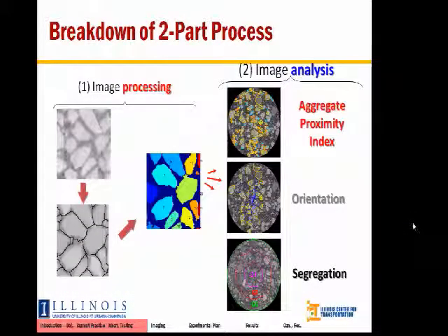But what is happening in a very generic sense, you've got the processing phase of the software, which will take your captured image, whether captured from your iPhone, a digital camera, a flatbed scanner, or one of your planar images from a CT scan. You can take one of your cross sections. It will end up going through several filtering stages for processing to define specific regions of interest. Okay, those regions of interest in this case end up being numbered as aggregate, so we will define aggregate versus non-aggregate and take that to the right side of the screen or the analysis phase.